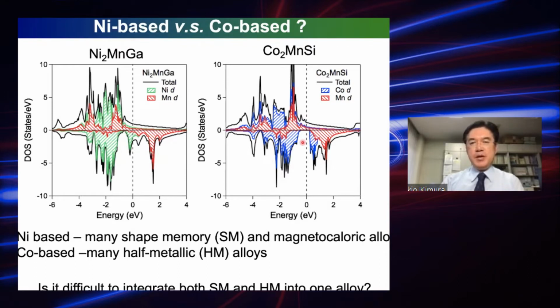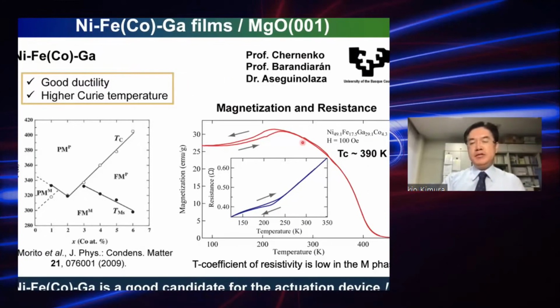So these results may indicate that it may be quite difficult to integrate both shape memory and half metallicity in a single compound, for example. So first, I'd like to remind you of some old work which was done by us and Professor Chernenko's group for nickel iron gallium films deposited on magnesium oxide substrate. The film sample is very, very important for application.